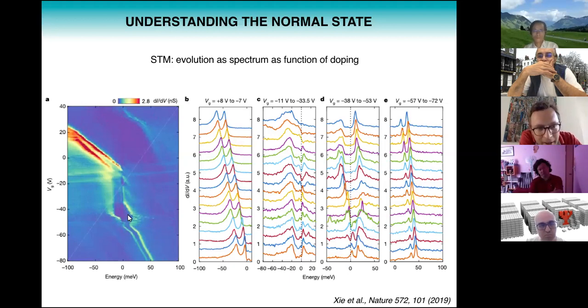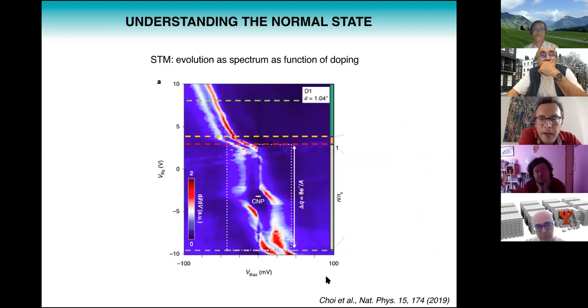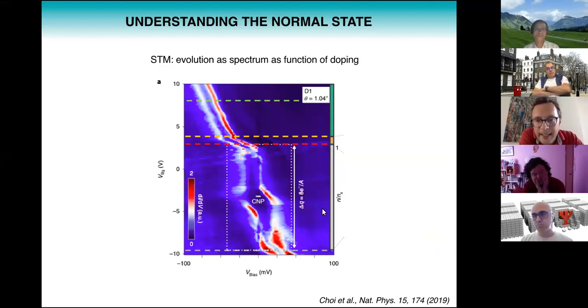Then again, there's a short region of pinning when the Fermi level hits the other Van Hove singularity. And then again, you have completely emptied out the flat bands, and you again get a dispersive tunneling spectrum. And finally, I want to show you a measurement from the group of Nadj-Perge at Caltech, which sees something quite similar. So again, a dispersive tunneling spectrum when the flat bands are completely filled, then you get Fermi level pinning, then again dispersion near the charge neutrality point, another region of pinning, and then again dispersion. So this is the state of the experimental knowledge of the normal state.